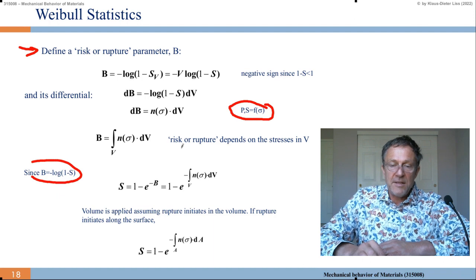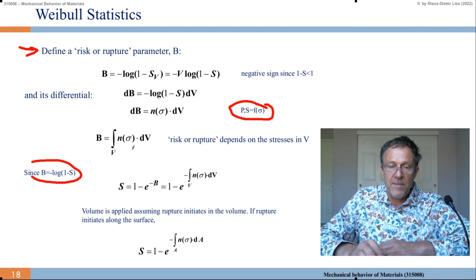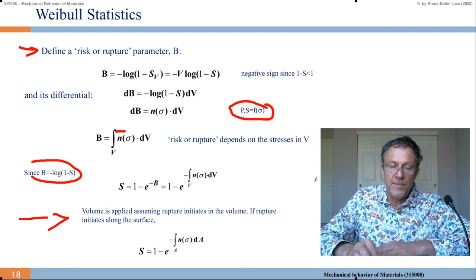So the risk of rupture depends on the stresses in the volume V. And of course, it depends on the distribution of the stresses in V. So volume is applied, assuming the rupture initiates in the volume. And if the rupture initiates along the surface, then we put the surface in. So we integrate over the surface A.